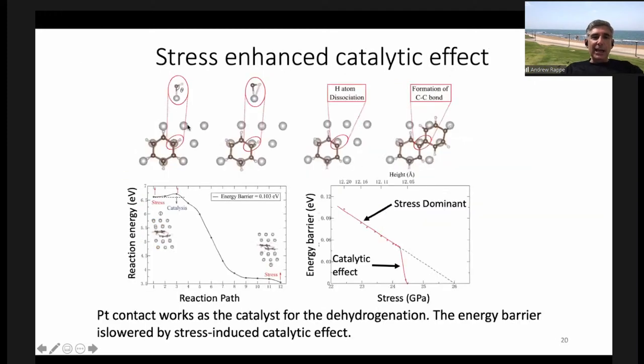Okay, so then we analyze for the platinum, how does the stress influence the reactivity and how is there also a catalytic effect? So I said to you that the molecule made a bowl shape. If you look at it from the side, the carbons bond to the platinum and the hydrogen is pointing up with some angle above 90 degrees. But as you compress it, the hydrogen is driven back down to being almost flat. And that means it makes a stronger bond to the platinum. And then the hydrogen atom can dissociate. And pretty soon after that, the carbon that lost the hydrogen goes to bond to a neighboring phenyl that also lost a hydrogen. And that's how it works.